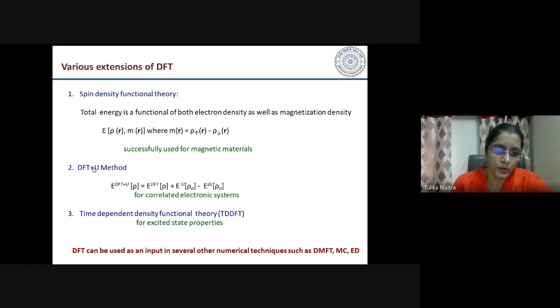Here this U can be calculated directly, there is a technique called constrained DFT calculation. From there you can calculate the U, or you can use it as a variational parameter to see where the experimental results are matching with your U parameter. Okay, so you can use it as a variational parameter, or you can directly calculate from the ab initio calculations like constrained DFT, or you can take it from experiments.